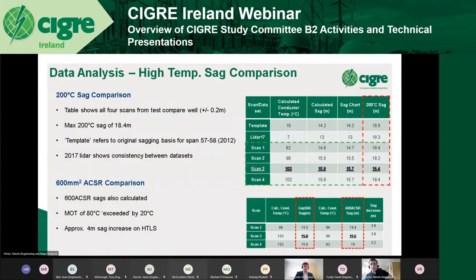So in the table on the top there, we've listed out each of the 4 scans and the 2017 LiDAR, and we've also included the template SAG for reference. So really we're interested in the right-hand side column, your 200 degrees SAG column. That's where we've taken every data set, done the graphical SAG, calculated the conductor temperature, and projected it out to 200 degrees Celsius for comparison purposes. And you can see there that there's quite good correlation across all data sets.